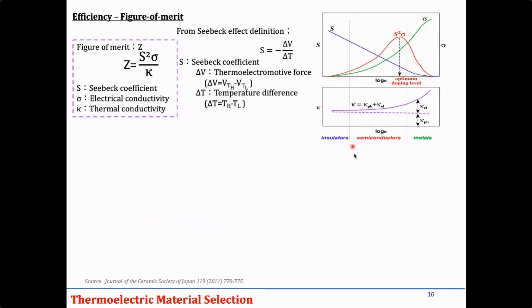So we always rely on semiconductor materials, which have an optimum condition for the highest efficiency. If you want the highest efficiency of Z, we always go with the optimum doping level, where the carrier concentration should be 10 power 18 to 10 power 20. Whenever we have N-type and P-type carrier concentration of 10 power 20, it is very good for thermoelectric application.